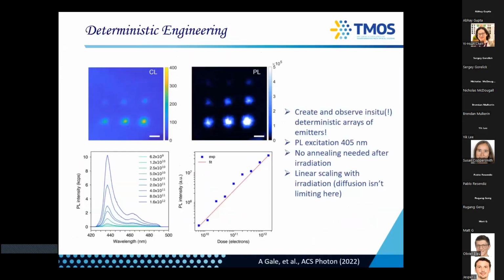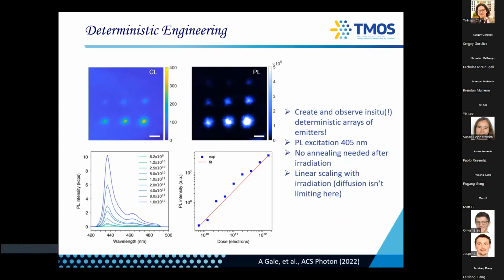So how do you generate these emitters? You just sit with your electron beam and irradiate. As you increase your radiation dose, you increase your defects and the luminescence intensity. The important bit here is that there is no annealing whatsoever, and it scales linearly. What it means is that there is no diffusion limiting factor here. Typically, for most defects there are a lot of clusters around. So you maybe have a nitrogen vacancy, like in diamond, where you would need to anneal to bring the vacancy to your nitrogen. In this case, there is no annealing. Remember, this is a very low energy electron beam, so we don't really kick any atoms out. There's not enough energy. We only locally break maybe a bond that is reconstructed straight away. But you can generate those defects with very, very high probability.